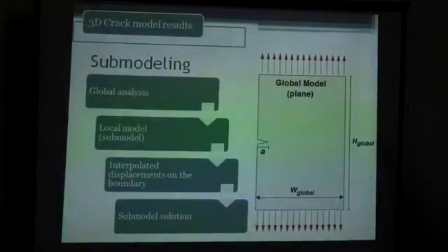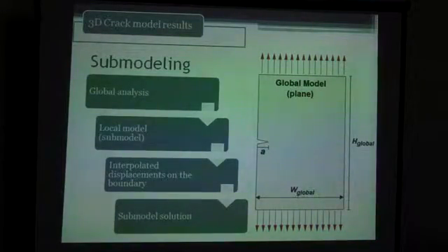Let's go straight to the cracks now. So here is how we conducted the calculation. Why are we using linear elastic calculations? We've worked with both linear elastic and elastoplastic finite elements. Most of the calculations we want to validate are based on the linear elastic hypothesis, if you have a small plastic zone. Since our group is focused on finding and predicting fatigue life, we need to see if the classic methodologies based on linear elastic fracture mechanics can be applied.